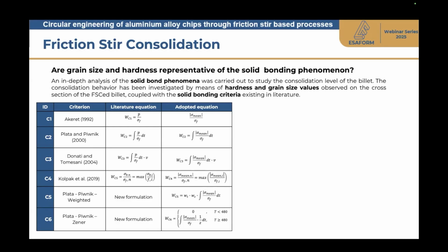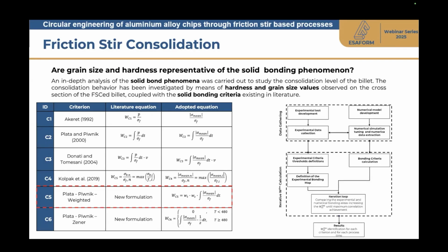Actually, we used several criteria proposed in literature, and we also gave some new formulation with introducing new parameters in order to have a proper map of what happens during the process and which are the actual conditions which permit to get an effective local bonding of the metals during the process. The criterion which demonstrated a very good behavior in this process was this Plata and Piwnik, a weighted Plata and Piwnik with a new formulation which permitted to have the best overlapping between numerical prediction and experimental validation.